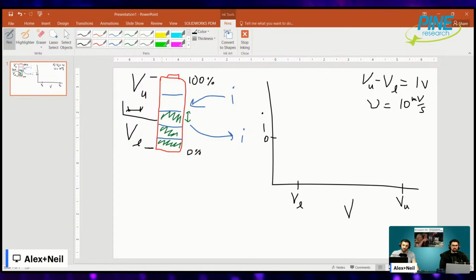So if you think charging your battery from 0% to 100% in a minute and a half sounds reasonable to you, which it shouldn't, then you're going to be in trouble, right? This is why, at the very least, if you're going to do CV, it's got to be very slow. So one of the answers, Jesse, that I have to your question or your point here could be that people say it's a problem. It might be because they're scanning way too fast. Because when you apply a current, the voltage will go up or down at some rate, and you usually make that a moderately slow rate.